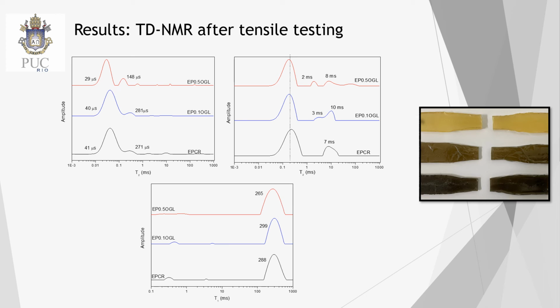The TD-NMR results display in more detail, in relation to the MSE FID, a tendency of T2 reduction in the same region of the samples containing graphene, mainly in the sample that has 0.5% of graphene. However, for the region of high mobility analyzed by CPMG, a mobility gain behavior is observed as a function of the graphene concentration even after the deformation of the material, with new relaxation domains appearing with relaxation times of almost 100 milliseconds for this 0.5 addition of graphene.